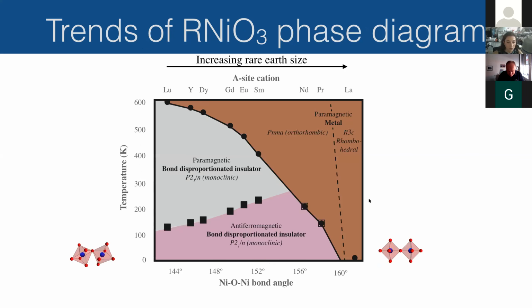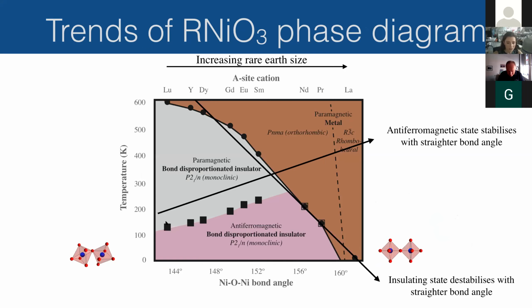Okay, so there are some overall trends. Let's just mention them briefly. So we have the different transitions. The metal insulator transition decreases in temperature as you increase the nickel-oxygen-nickel bond angle. And this can be understood pretty simply as the bandwidth getting bigger as you go to the right here. So the insulating state is getting less stable. On the other hand, you've got the antiferromagnetic transition, which is increasing in temperature as the nickel-oxygen-nickel bond angle is increasing. So this is just through the magnetic exchange. And finally, you have here, at this point, that the antiferromagnetic transition starts to decrease again in temperature, and this is simply because the metallic state is probably suppressing the antiferromagnetic state through charge fluctuations.